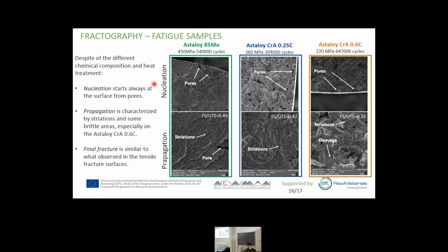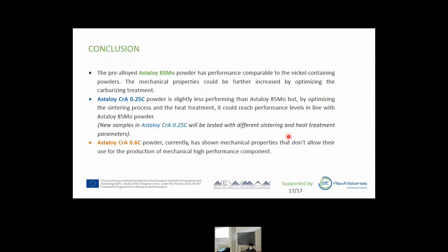And once more, the fracture surface can explain the reason for this different ratio. In fact, despite the different chemical composition and heat treatment parameters, the nucleation of the fractures always starts near the surface from the pores. But in the propagation area, in the two powders with a ratio of about 50%, we have striations and, of course, pores. While in the last powder with the ratio of about 33%, we have striations and a lot of brittle areas with cleavage. The final fracture surfaces are similar to the surfaces observed for the tensile samples.